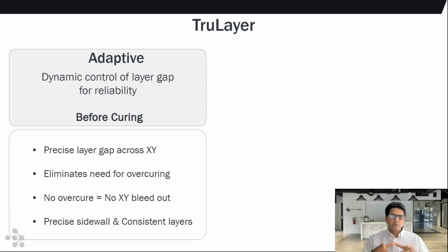And as a result, there is no bleed out in XY because there's no overcuring required. And since there's no bleed out in XY, we get pristine sidewalls, extremely accurate dimensions, and the flatness because of the peel off that we do differently. As such, what Eric was mentioning is the part quality is extremely detailed, extremely accurate, high resolution, and quite different from what we get today from conventional systems.